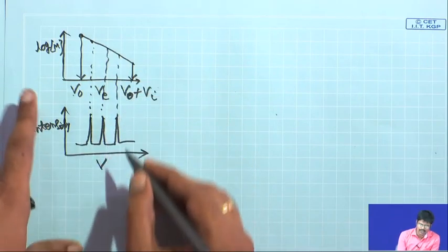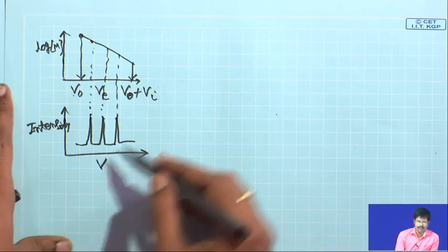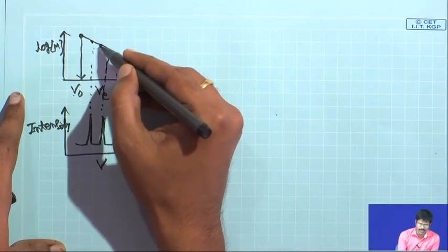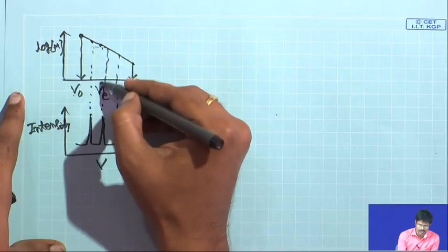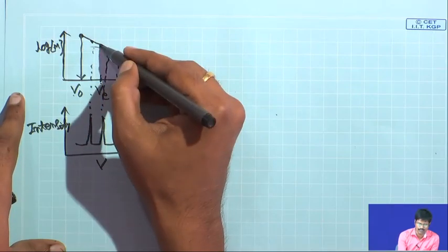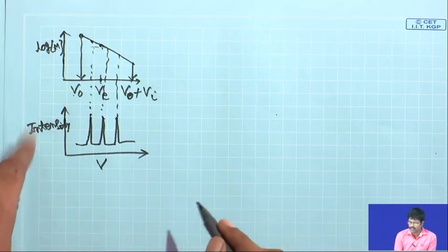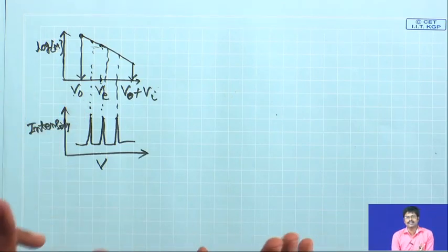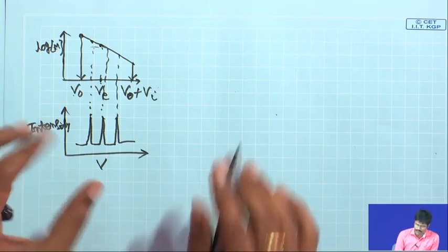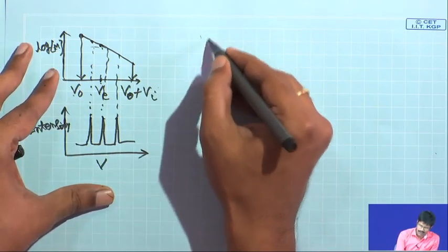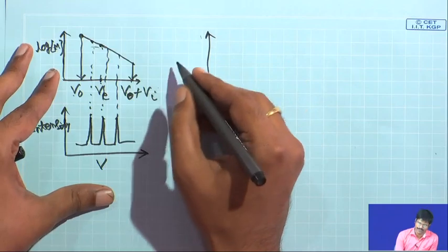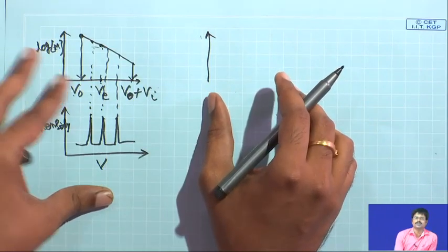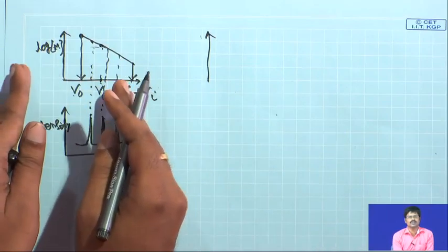So, if you now have an unknown molecular weight, you can find it from this particular curve with respect to the elution volume, because you know the elution volume. From the point where it falls on this curve, you can find the molecular weight of the sample. The final thing I want to tell you before I conclude this class is that on the y axis you have detector response, and on the x axis you have elution volume. That elution volume you have now correlated with molecular weight.